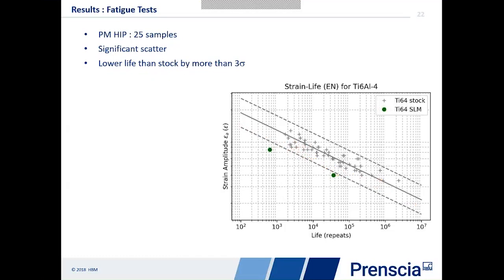Now, right now, to date, we've only got 2 samples using selective laser melting. And these are below that 3 sigma level here. Now, partly that's why we've only tested 2 levels, and partly this is because these are not hipped yet. So the idea was to try and find a base parameter so that we can look at hipping. And it's not just one type, but several types of hipping and post-treatment to see which ones are likely to give us better results. So right now, the results aren't bad, but we only have those 2. So that's something we're going to concentrate on in the next few months.